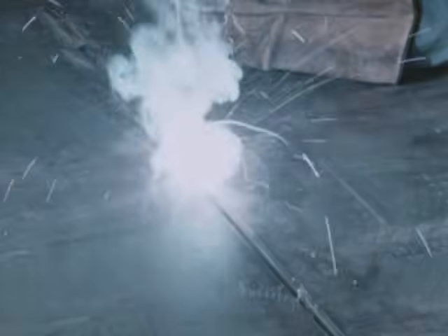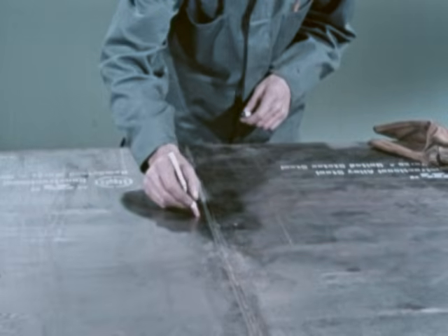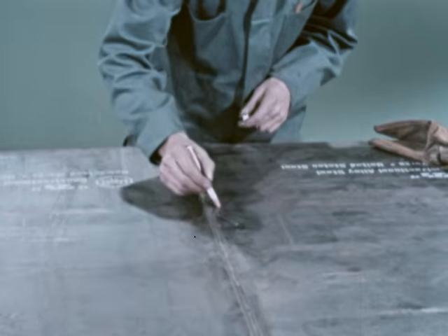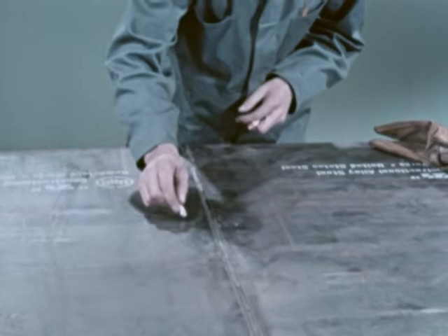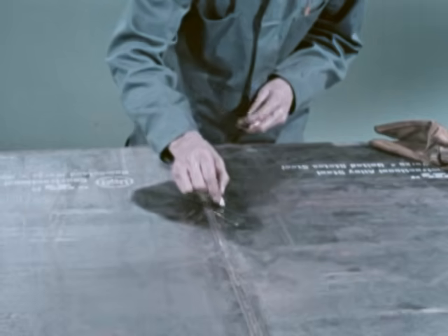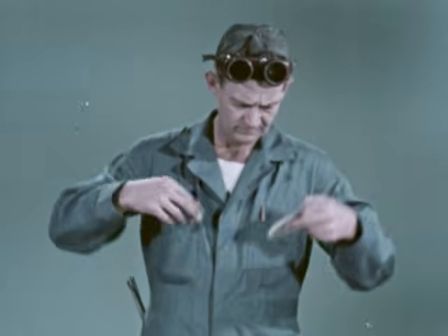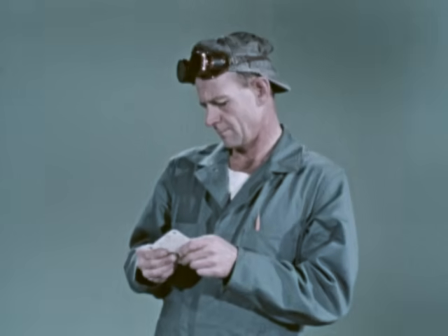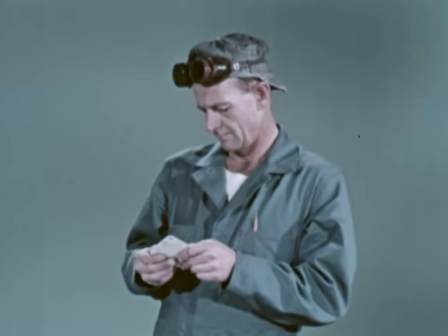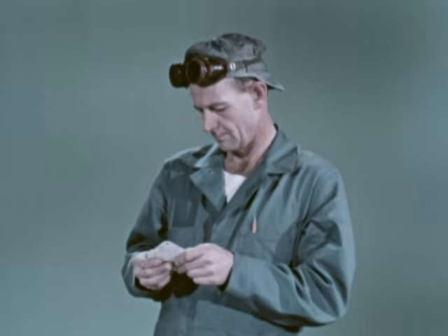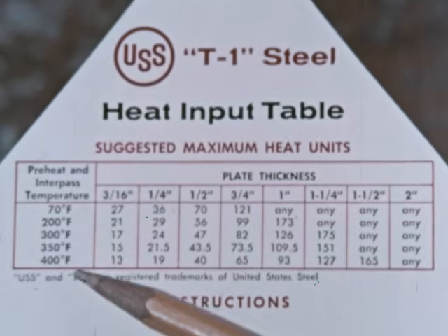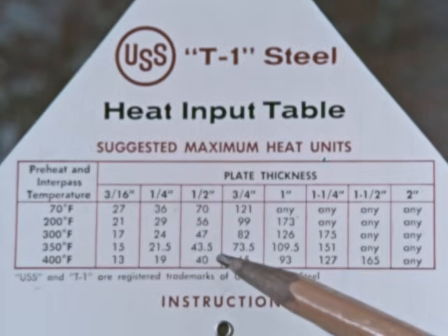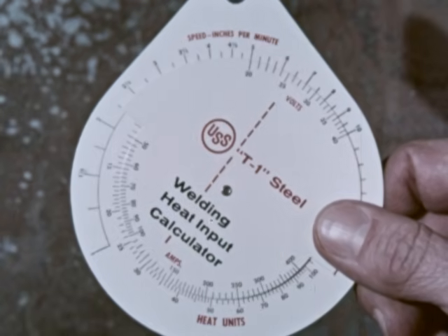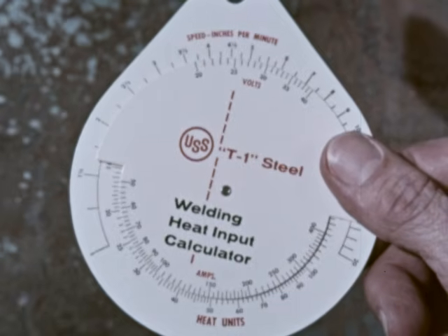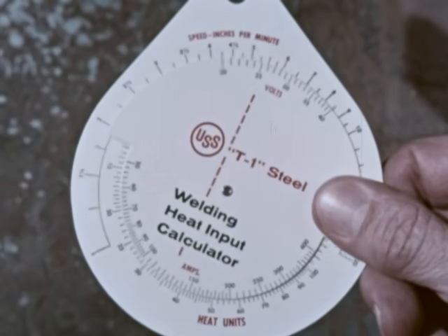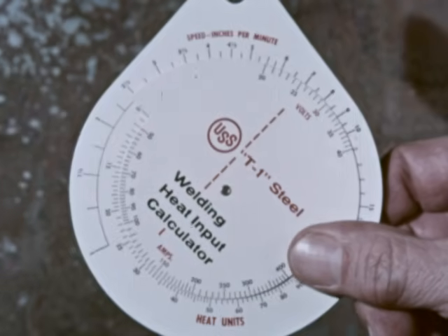When you've finished your first pass, your crayon shows the temperature has gone up from 300 to 400 degrees Fahrenheit, 100 degrees higher than the preheat and interpass temperature on which your heat input calculation was based, 47 maximum heat units. An adjustment is indicated. You either lower your heat input from 47 to 40 units by lowering the amperage to 170 at the same speed, or increasing the speed to 7½ inches per minute with the same number of amps.